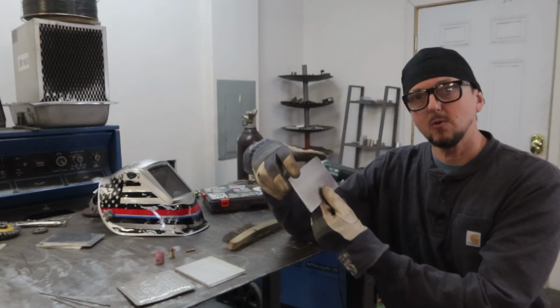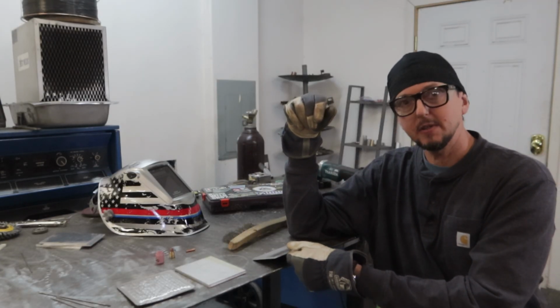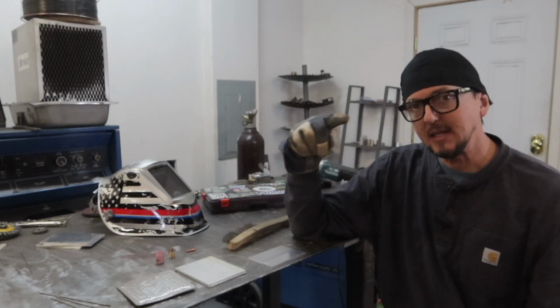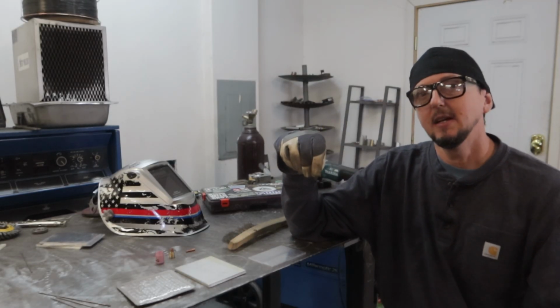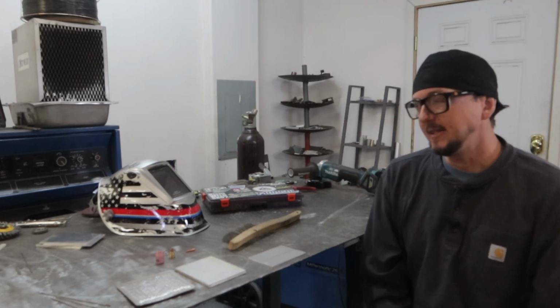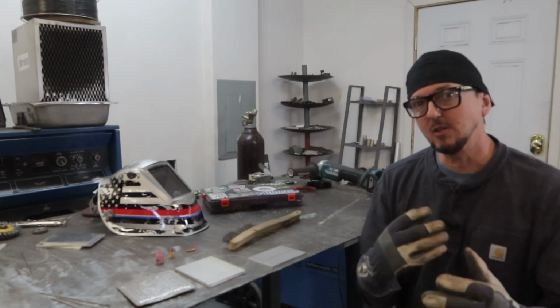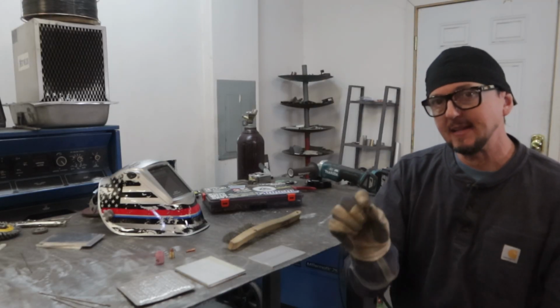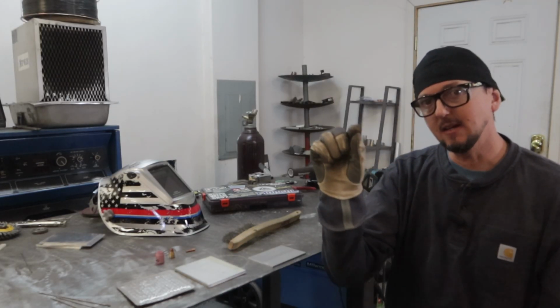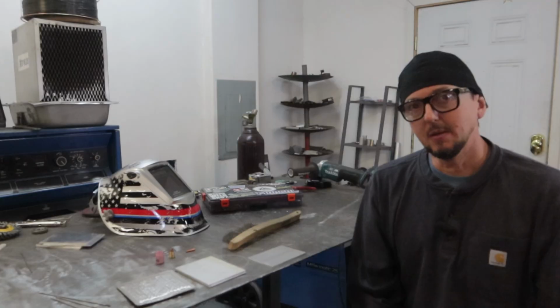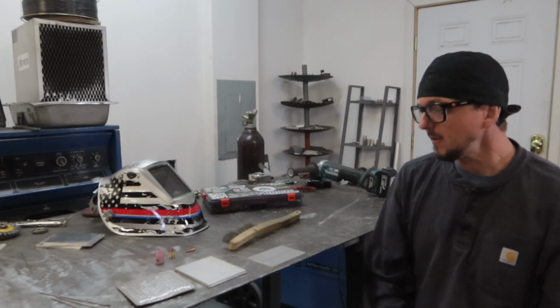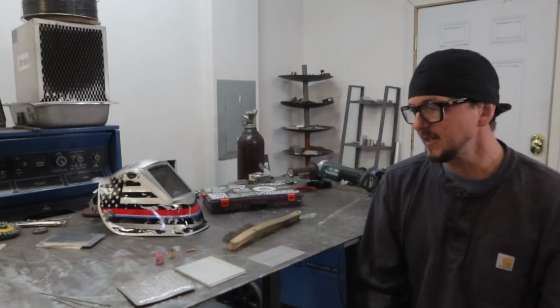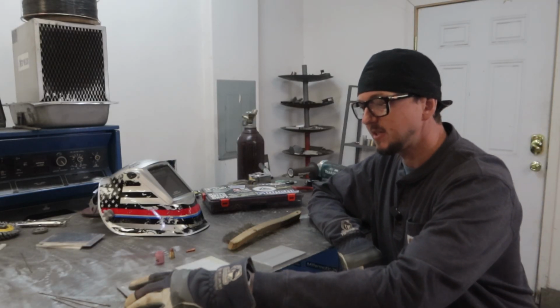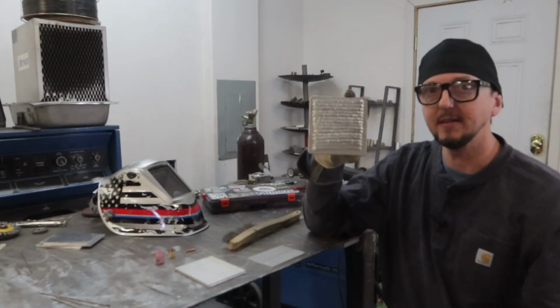Okay, there is going to be some oxide layer that's left over in there, but the DCEP side of that AC welding circuit gives us some cleaning action which will break that up further, and that's that sort of hazy line that you see on the outside of your aluminum welds, the cleaning action that I'm talking about. Okay, so that's how we'll prep the material first, and then we're going to start to put these beads on,